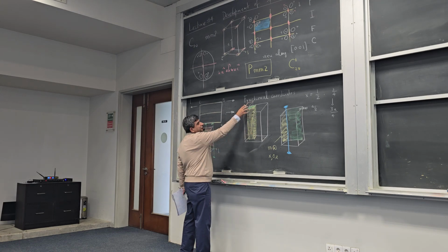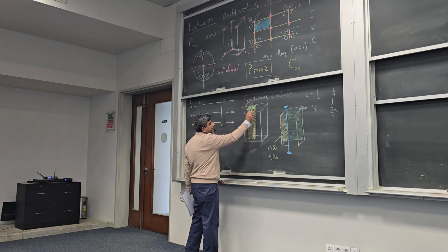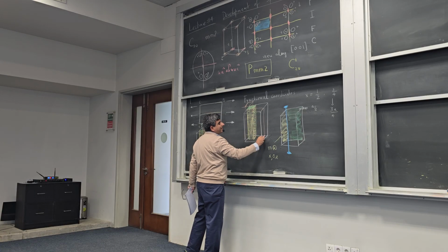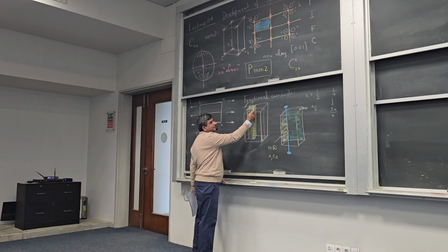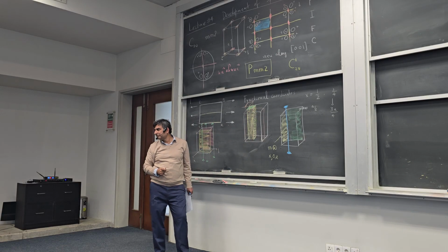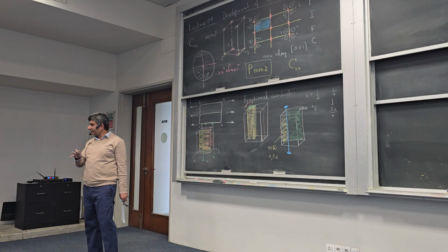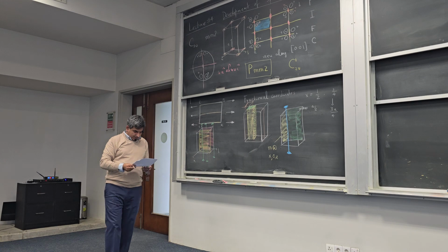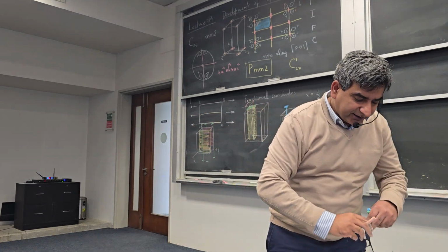Okay? When this cuboid is translated by the translation vectors, you're actually filling up this section of the unit cell. Correct? So that has created another 2-fold axis of rotation at this intersection. So once you define the asymmetric unit together with the symmetry operations and all the generators, you'll get all the additional symmetry elements.